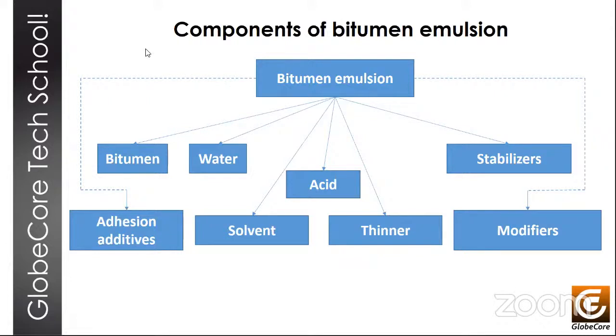Solvents or thinners — that is a light oil fraction with a boiling point of 140 to 220 degrees centigrade. It's added in the amount of maybe 0.5% to 3%, and it's used to help create a homogeneous system.